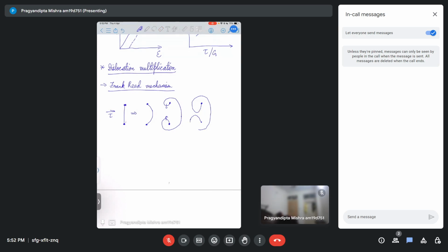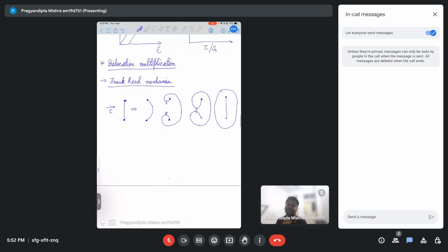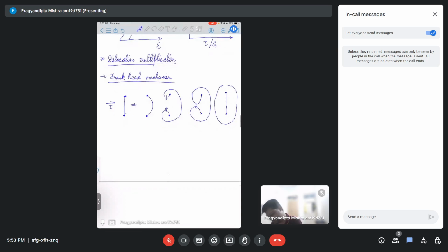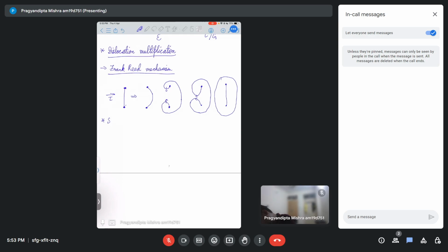But one important thing to note here is these two points which are coming closer have opposite signs of Burgers vector, right? So they will annihilate each other and mix. So in the end, we will see a dislocation here at the center, and another dislocation which is around it. So what essentially is happening is that as stress increases, dislocation density will also increase.